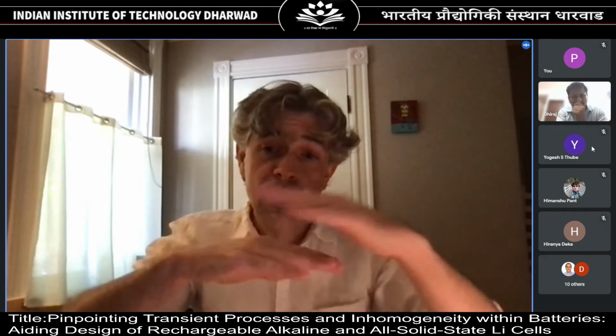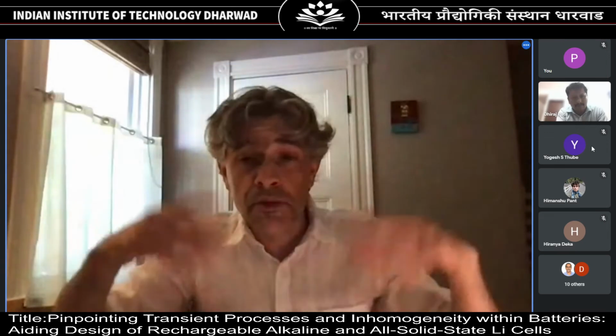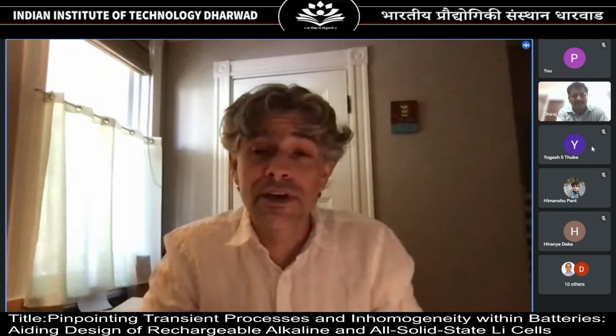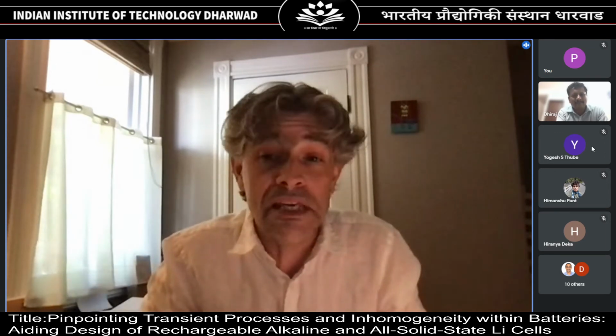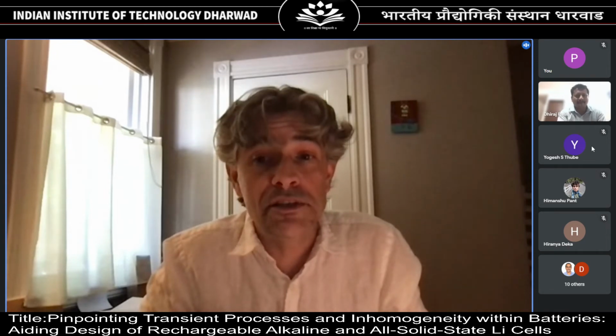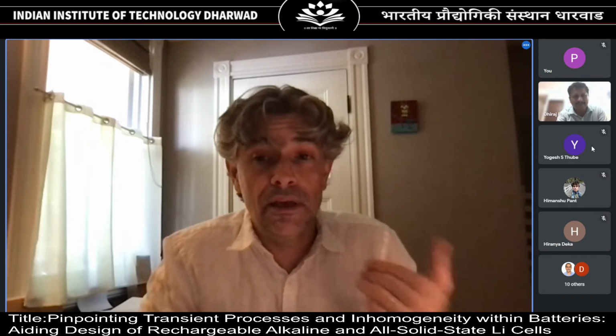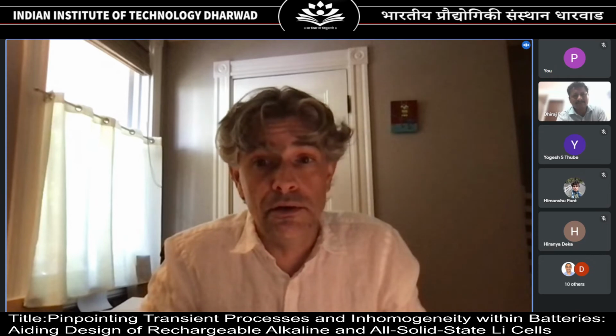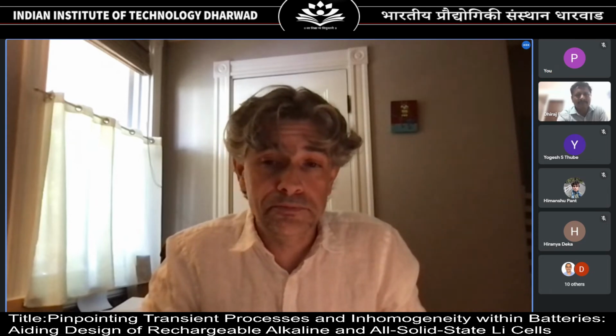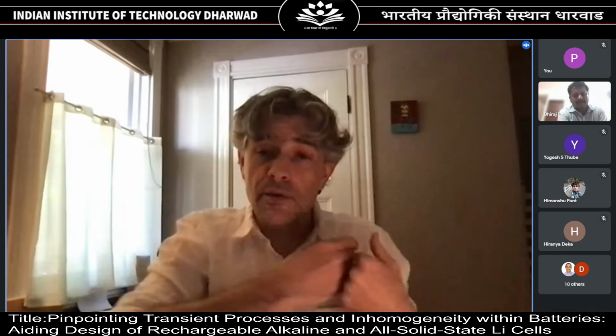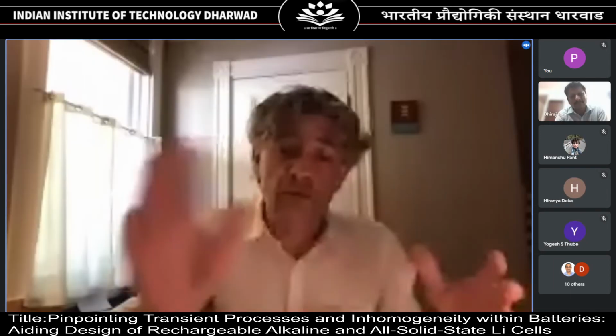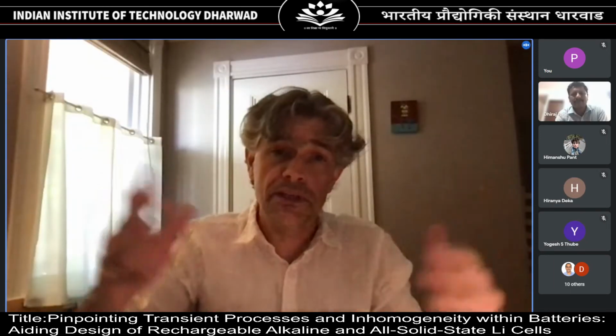I said that our polymorph is a layered polymorph and that it cycles as layers. But the layered polymorph of MnO2 is not a commodity on Earth, right? So the industry of the world does not make a high tonnage, many, large mass of that material. But the gamma form of MnO2 is a commodity chemical, which is made many, many places. And so it is the cheap chemical to buy. So what we do in order to use that material is we put it in the battery and then we cycle it, we discharge it and charge it. And when it charges back up, it becomes the layered form, and then it cycles as that layered form.